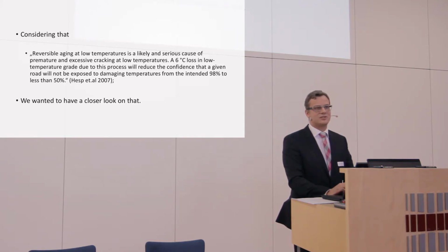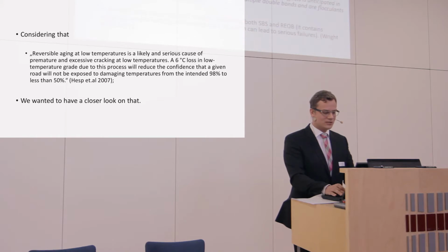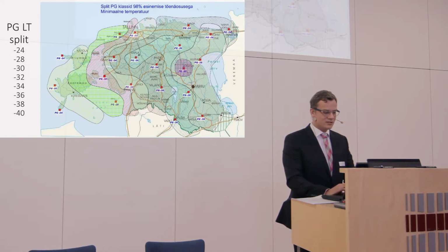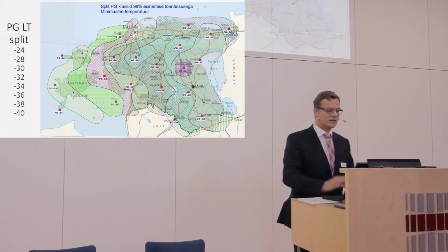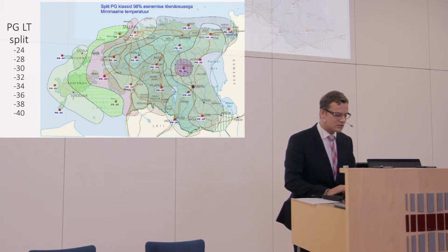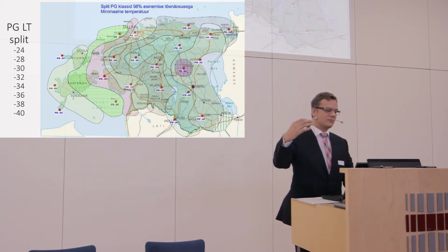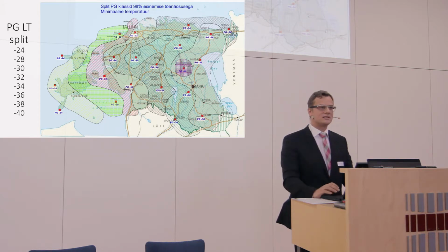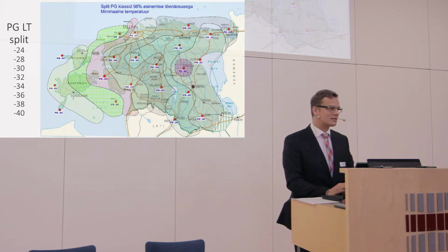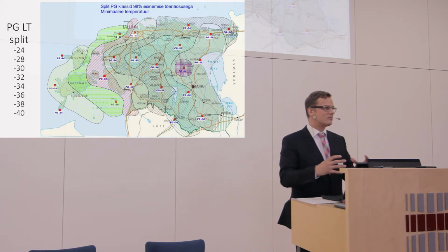to less than 50%. When we go back to this map here, as you can see, well, it is in Estonia, but here you can see the confidence that this temperature will not go up to minus 36 degrees, or this temperature goes up to minus 34 degrees. The confidence is 98%, though basically it never happens.